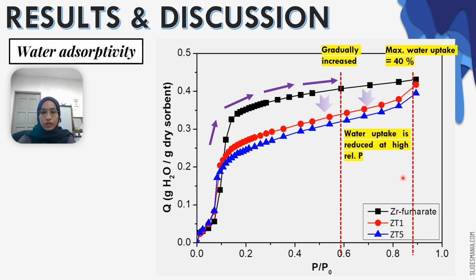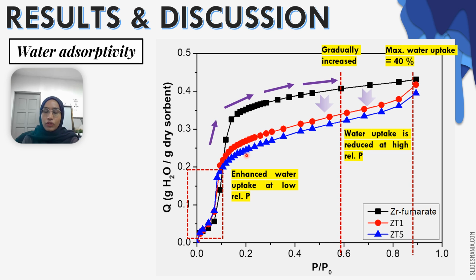However, upon hybridization, we can see that the water uptake for the ZT nanohybrids is reduced, especially at high relative pressure. But what I want to highlight here is the enhancement of the water uptake at a very low relative pressure, which is below 0.1. Even though it's not that significant, we can still see an improvement of the water uptake upon hybridization. We can see that in these highlighted sections. There is a little bit of enhancement of water uptake at a very low relative pressure. We need high water uptake at a low relative pressure because it is convenient for the application.